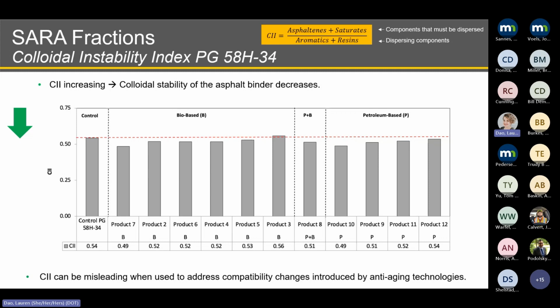And here are results for the PG 58H-34 binder, where we can clearly capture the effectiveness of these products, considering the colloidal stability of the binder. One thing that I need to mention is that we use solvent to separate the SARA fractions. Because these bio-based and petroleum-based treatments have components that have high polarity, they could be attached to the asphaltenes present in the binder, and therefore, in the first step of separation for the SARA fractions, they would be washed out with the asphaltenes. So sometimes we have to look at these results with caution because they can be misleading.